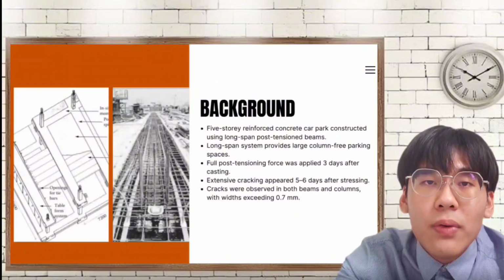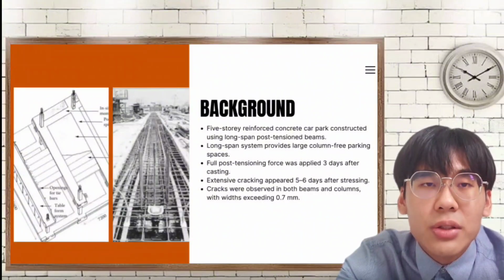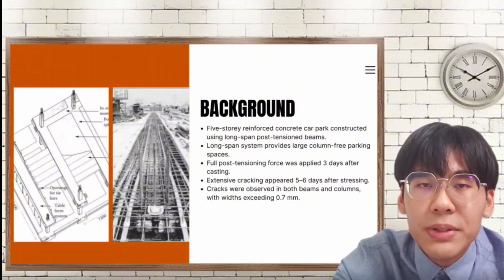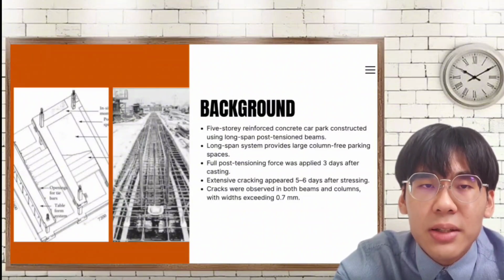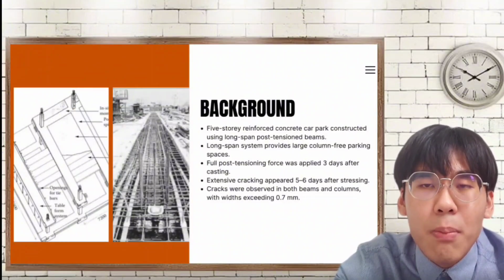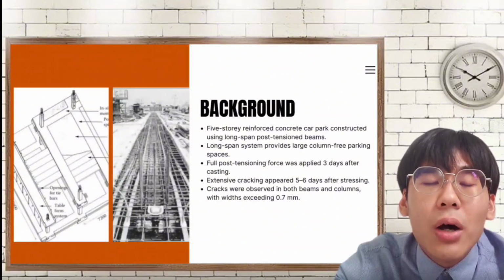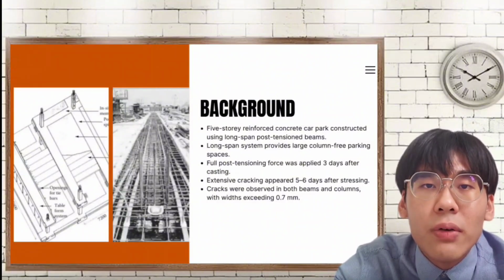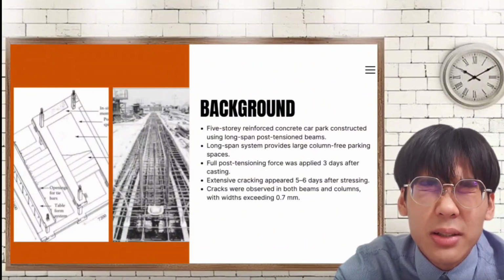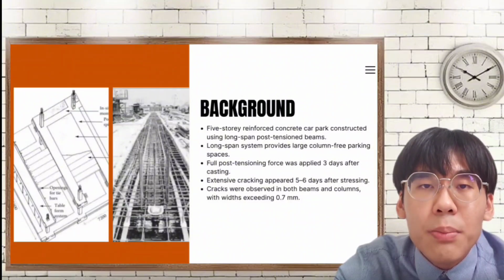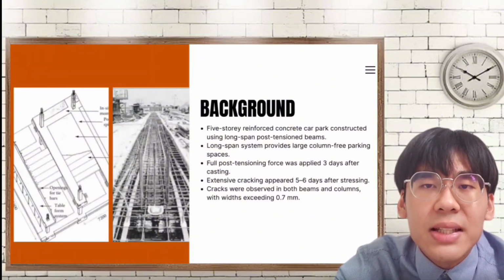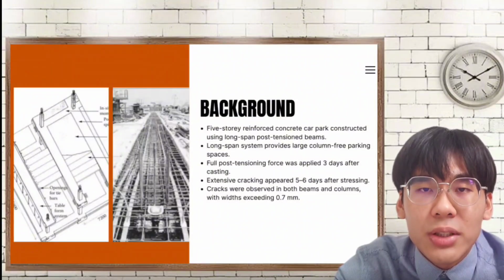The case study involves a 5-story car park construction using a long span post-tensioning beam system. Post-tensioning was selected because it allowed longer spans with fewer columns, creating larger and more efficient parking space. However, during construction, the full prestressing force was applied only 3 days after casting. Shortly after stressing, between 5 and 6 days, extensive cracking was observed throughout the structure.